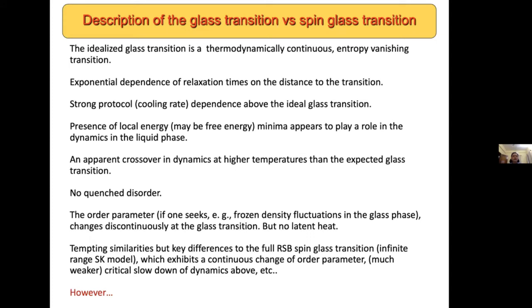And even though in the earlier literature, one did not think in terms of an order parameter to describe the glass transition, if one were to seek an order parameter, such as some measure of frozen-in density fluctuations in the glass phase, this order parameter, one would conclude, changes discontinuously. And there is no latent heat at the transition.